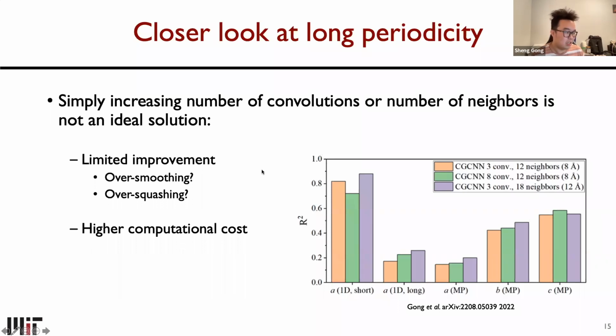And we think that this limited improvement might come from the phenomena of over-smoothing and over-squashing, which prevent the use of very deep GNNs. And even if this limited improvement can be addressed by overcoming the over-smoothing and over-squashing problem, we still know that the computational cost of graph neural network directly depends on the number of convolutions and the number of neighbors. Therefore, by increasing these two hyperparameters, we inevitably increase the computational cost, which might not be an ideal behavior for some cost-sensitive applications such as machine learning force field.